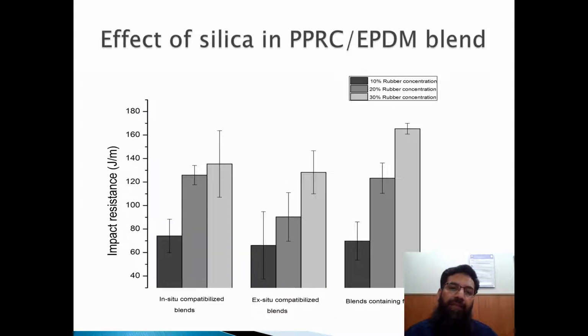The impact strength also increases in the similar kind of the blends with the incorporation of the silica as a nanofiller. So there will be the effect of the elastomer as well, because we are adding the EPDM in the PPRC. So with the increase in the EPDM content, there will be increase in the impact strength. But if we compare these with the other compound which are also having the similar kind of the EPDM loading, when we add the silica, the impact strength of our compound also increases, which shows that the silica can also help us in getting the better impact strength in the different plastic parts, which can be potentially used for different applications for the automotives.